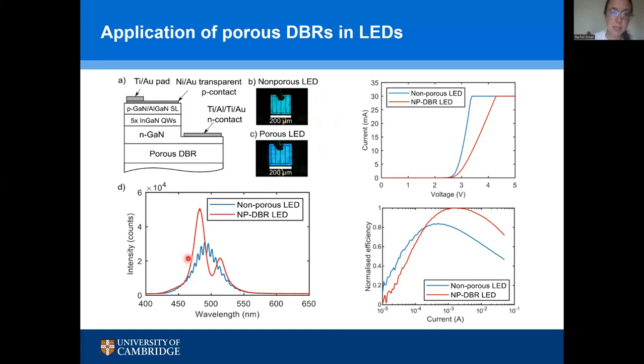And what we can see is that when we introduce the porous layer, we increase, for the same drive current, the amount of light we're getting out of the device. And that's simply because we're reflecting out light that would otherwise be lost because it's emitted from the quantum wells down into the substrate. And we can see that if we work out an efficiency curve, that increase in light extraction is increasing the efficiency of our device, which is exactly what we'd expect it to do.